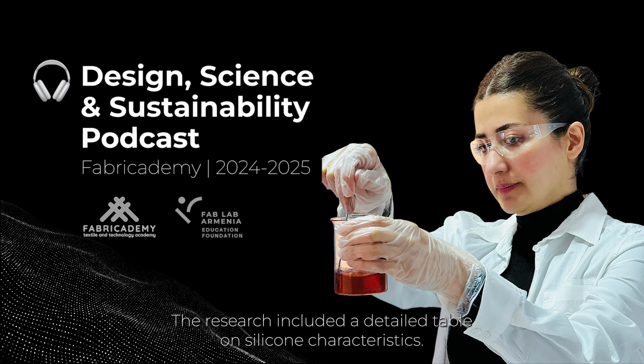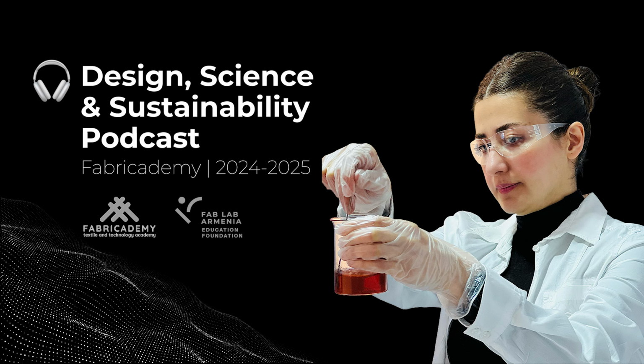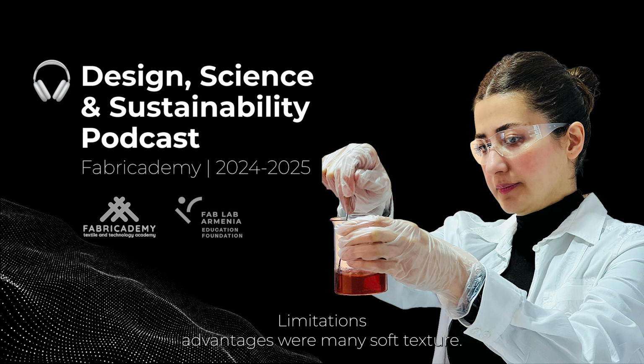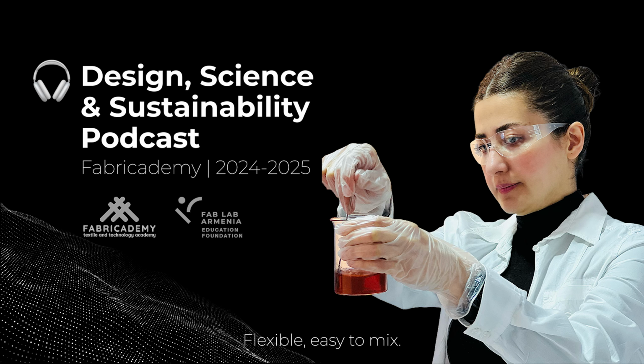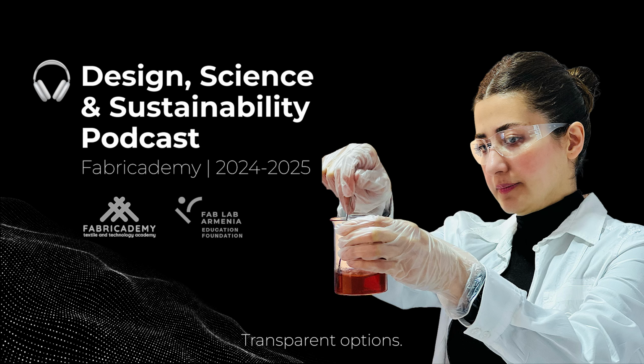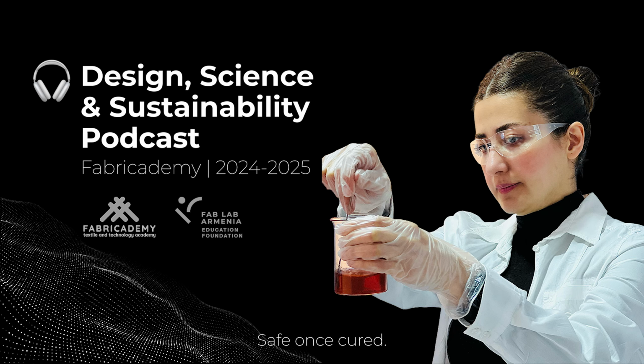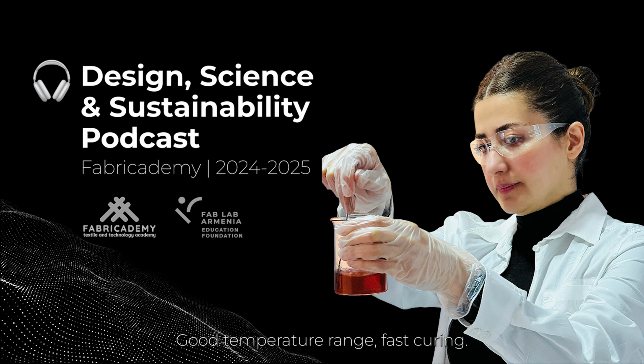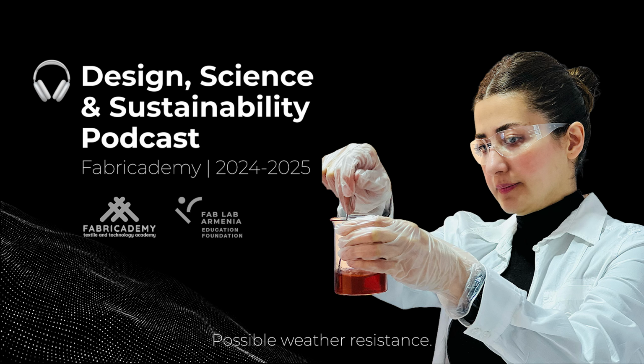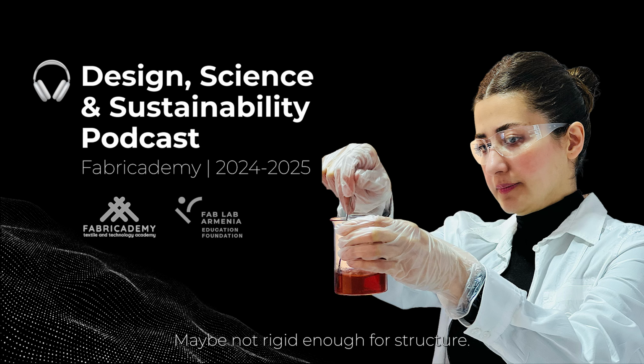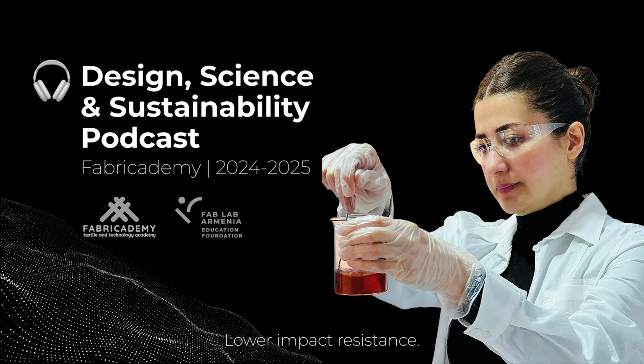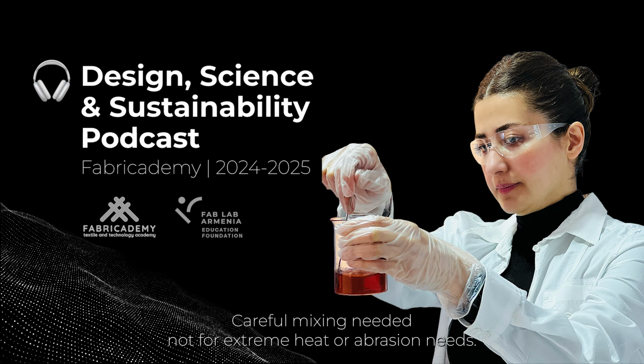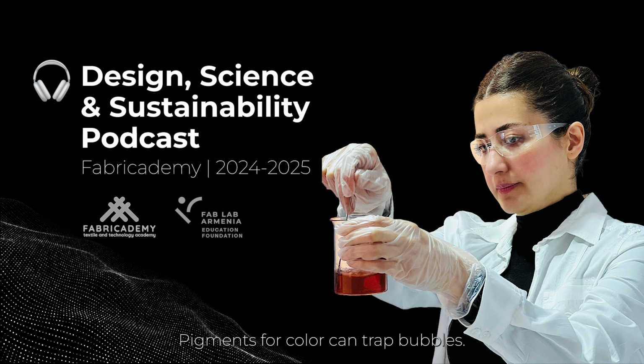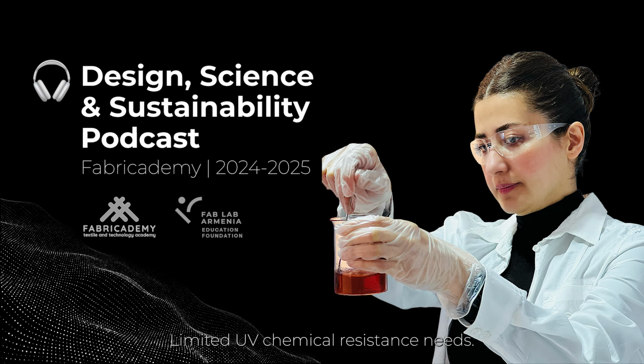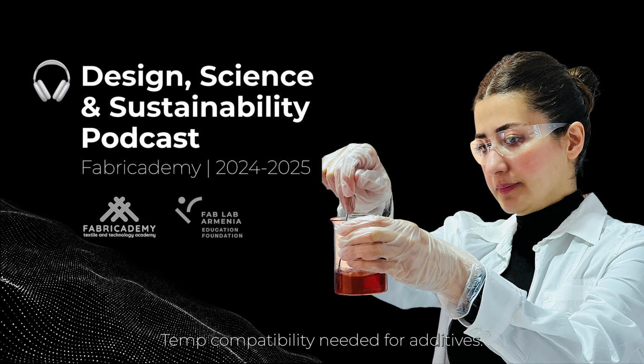Lots to consider. The research included a detailed table on silicone characteristics, advantages, limitations. Advantages were many. Soft texture, flexible, easy to mix, durable against abrasion, transparent options, low viscosity for detail, safe once cured, good temperature range, fast curing possible, weather resistant. Sounds great. Downsides? Limitations included, maybe not rigid enough for structure, lower impact resistance, careful mixing needed, not for extreme heat or abrasion, needs pigments for color, can trap bubbles, uncured state can be irritating, limited UV chemical resistance, needs controlled cure temp, compatibility needed for additives. It's a balance. Good summary.